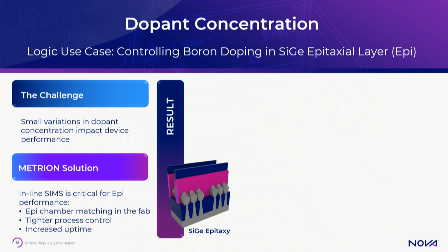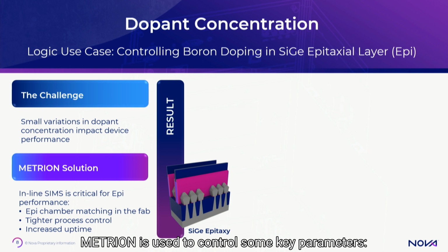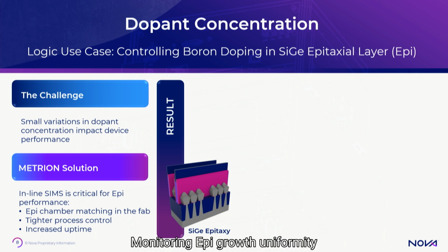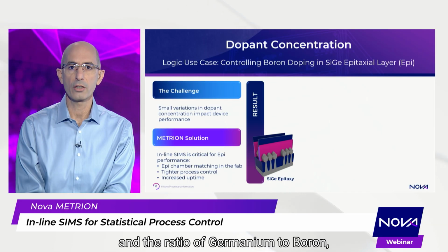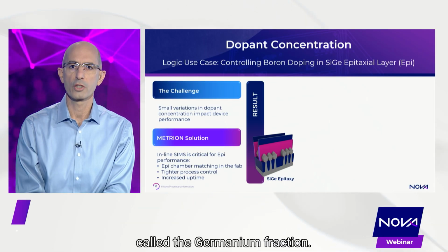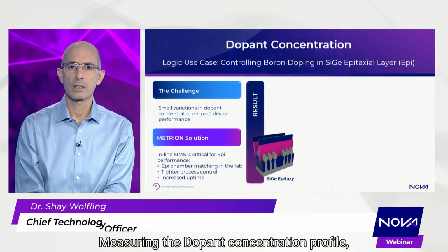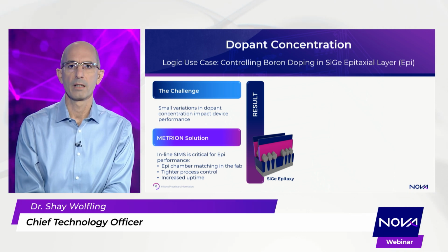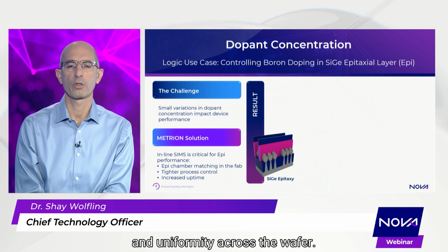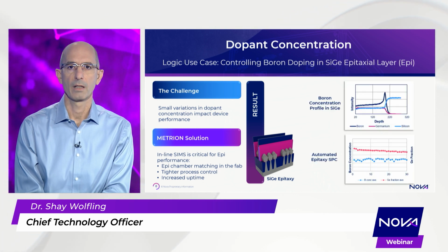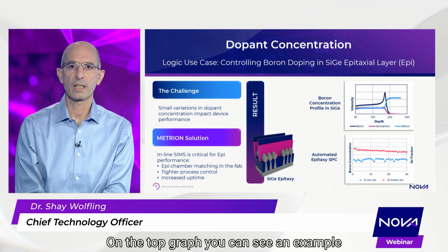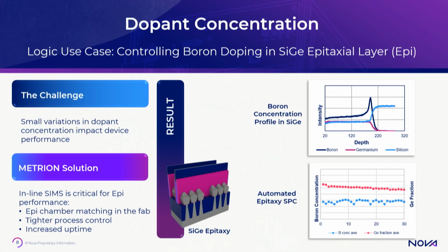During the epi process, METRION is used to control some key parameters: monitoring epi growth uniformity by tracking the germanium concentration and the ratio of germanium to silicon, called the germanium fraction, and measuring the dopant concentration, profile, peak concentration, and uniformity across the wafer. On the top graph, you can see an example of a single measurement of boron, germanium,